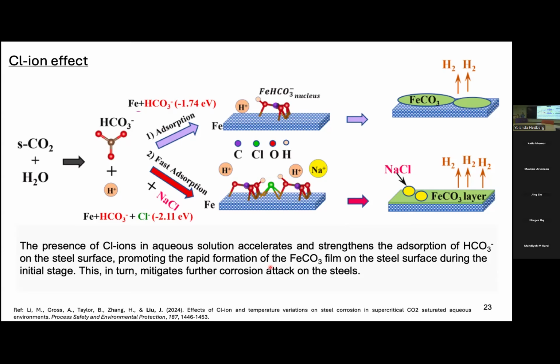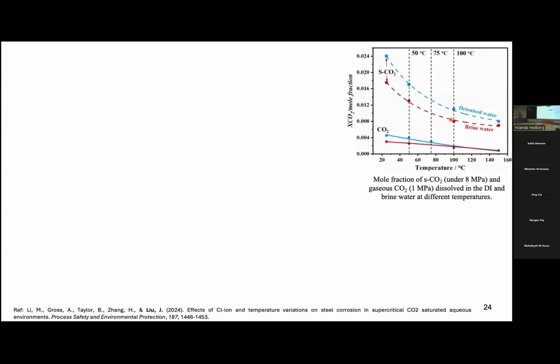And on the other side, we are injecting CO2 in the formation water or in the DI water, right? But there must be a solubility. So with sodium chloride, the CO2 solubility is way smaller compared to DI water. So you have less CO2 forming carbonic acid, so the pH is higher. If you compare this one, this line is the DI water line, this is the brine water line, right? So the solubility of CO2 is much smaller in brine water.